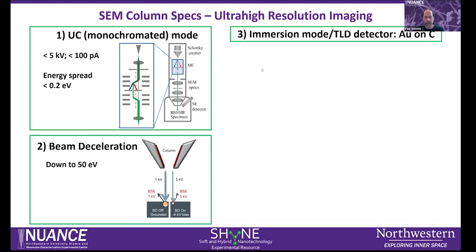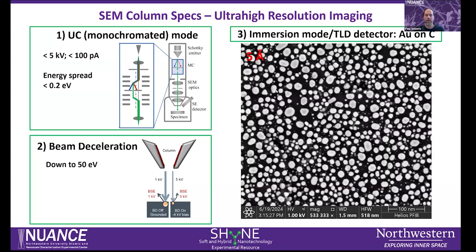The third requirement is you need to be in that mode I previously mentioned, the immersion mode, in combination with the through the lens detector. If you do that for a gold on carbon sample, then you can get a resolution of 5 angstrom. This is currently the only SEM in our facility with a monochromator present.